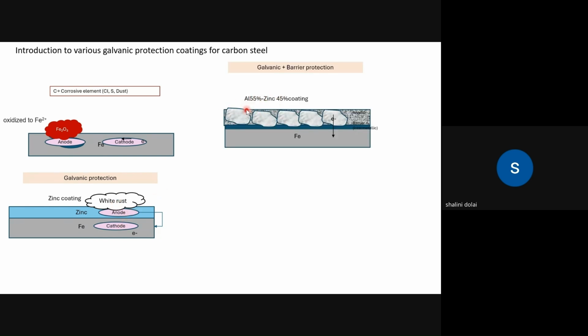So what we did, we went for another coating, which is aluminum 55% and zinc 45%, where zinc and aluminum both supply electrons to iron, but aluminum forms aluminum oxide in this process. Unlike zinc oxide, aluminum oxide is stable and forms a passive layer, so it delays my corrosion. But due to these big chunks of aluminum oxide layer, the coating was brittle. So whenever there was some mechanical impact, the coating was breaking and again the corrosion was happening.